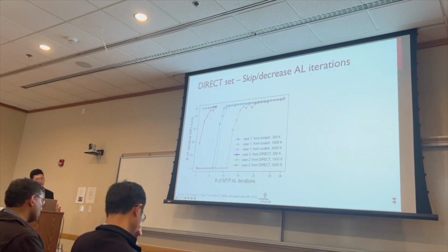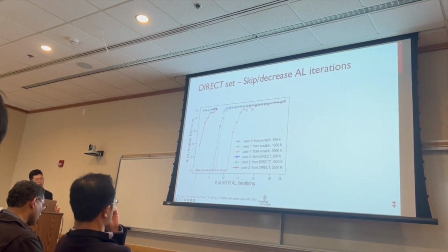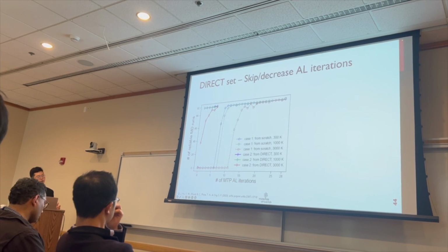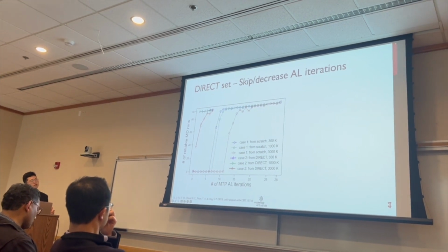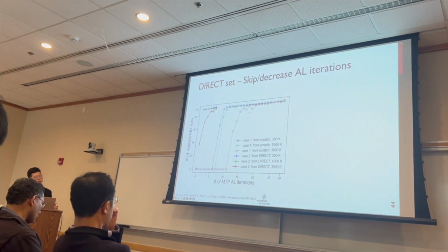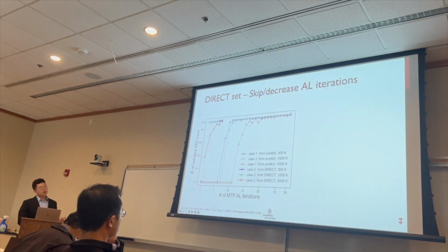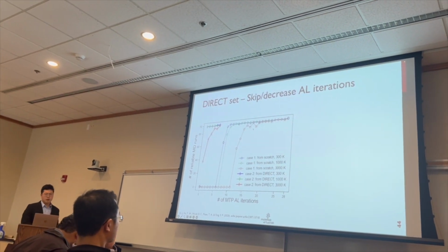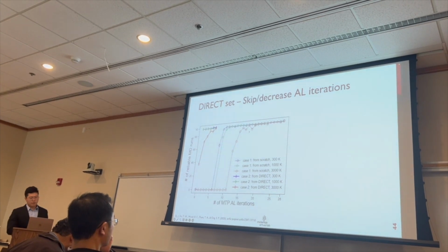For higher temperature, in this case 3000 Kelvin, we still need 5 iterations of active learning to get all the simulations reliable. But this is a few times smaller in terms of active learning iterations compared to active learning from scratch.